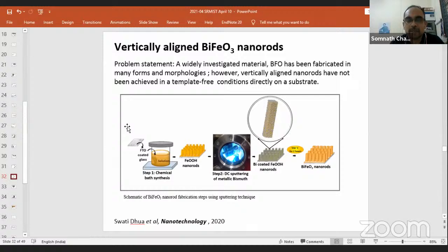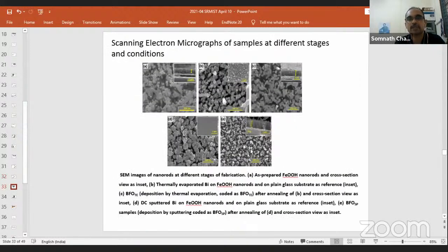We sputtered bismuth. I'm going over this quickly. We sputtered bismuth. We ran a very carefully programmed annealing, and the result is that what we got is the bismuth ferrite nanorod. So as you can see in the top view and the cross-sectional view, first we have FeOOH nanorod, we put bismuth, then after bismuth we anneal it again. As you can see, the top view, bismuth.